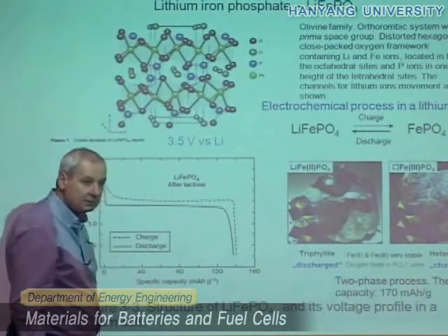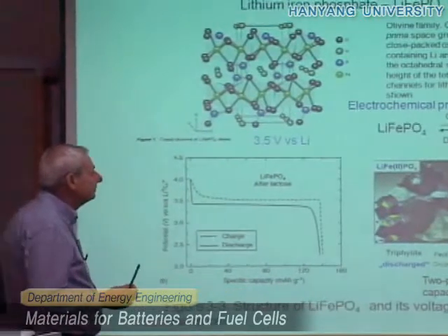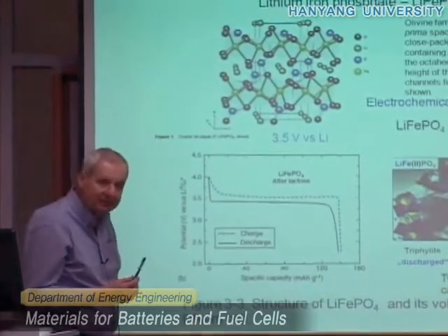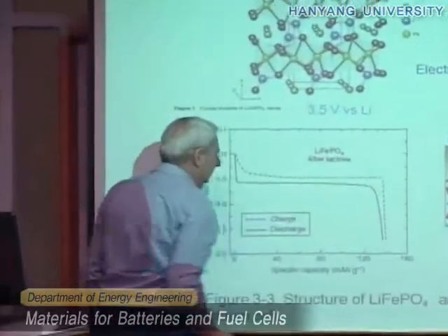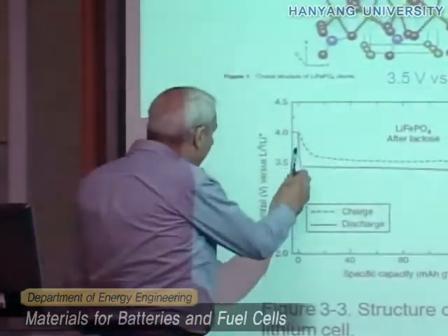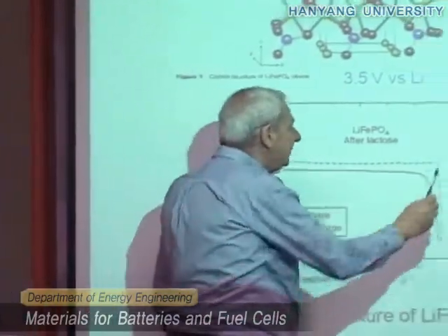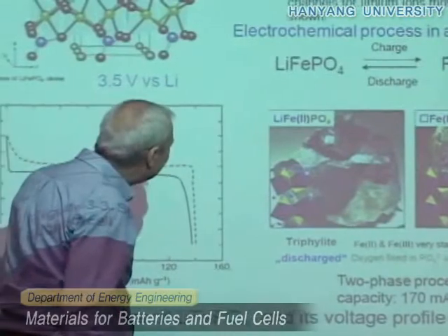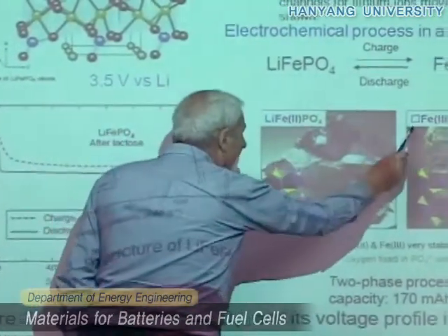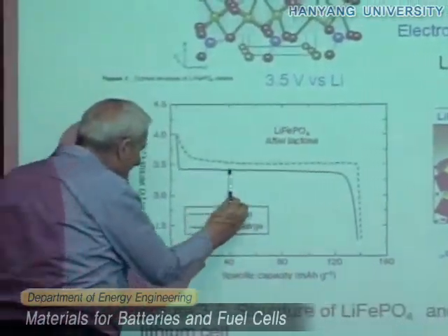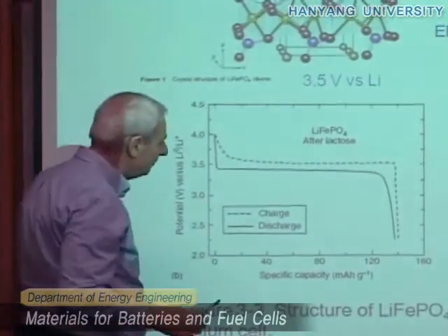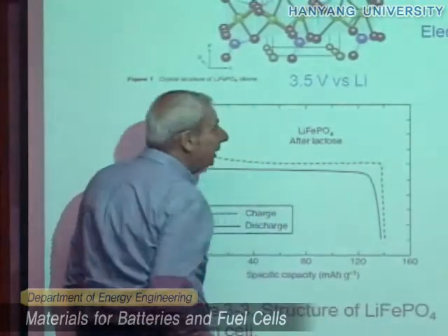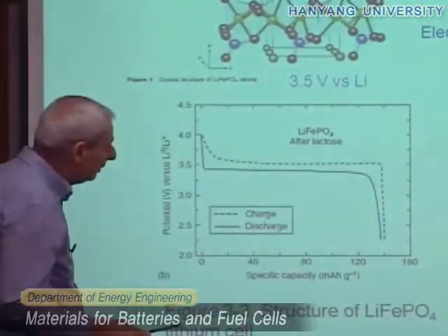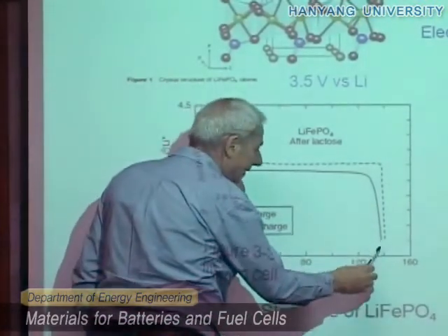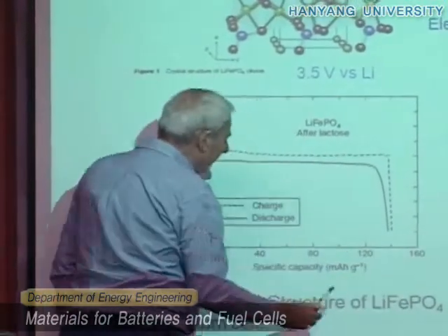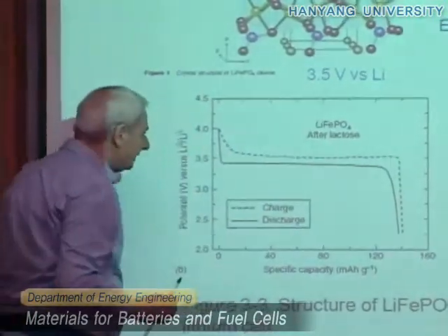So this is a two-phase process, and when we have an electrochemical process formed by the coexistence of two phases, we always have a very flat voltage. Okay? So you see here that when we remove lithium and we go from this phase to this phase, namely we pass from iron 2 to iron 3, we have a very stable voltage, which is about 3.5. Then here the process is completed at about 170. This will be less because this is a practical capacity, not a theoretical capacity. Then we can charge it back, going in the same direction.